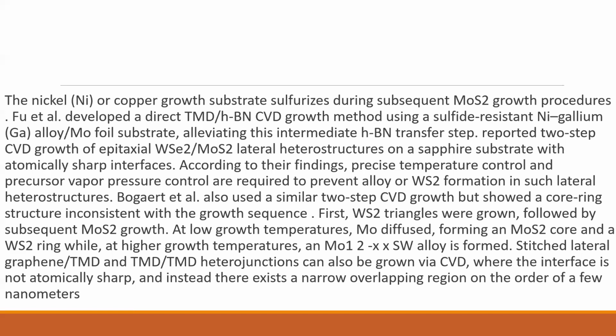atomically sharp interfaces. According to their findings, precise temperature control and precursor vapor pressure control are required to prevent alloy or WS2 formation in such lateral heterostructures. Others also used a similar two-step CVD growth but showed a core-ring structure inconsistent with the growth sequence. First, WS2 triangles were grown, followed by subsequent MoS2.